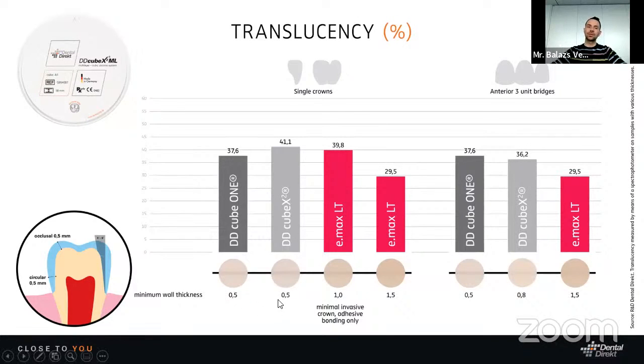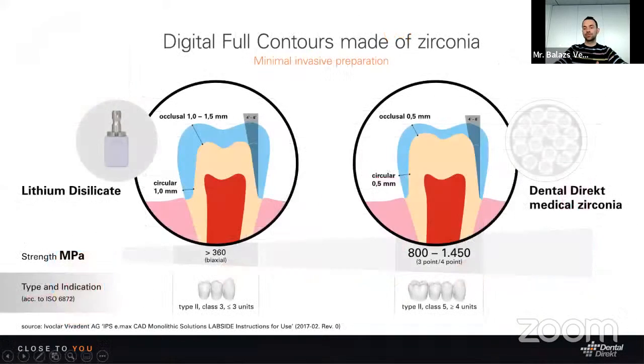It means thanks to the zirconia materials we have, we can reach the same aesthetic, but of course with minimal space. For a single crown or even smaller bridges, 3-unit bridges, we need in most cases 1.5 millimeter space. It means more work for the dentist. They have to prepare more of the natural tooth, and of course there is more material we have to build on to have the same reliable and aesthetic restoration. Which means for an e.max crown, for example, 1.5 millimeter. The same we can reach from our zirconia material with 0.5 millimeter space.